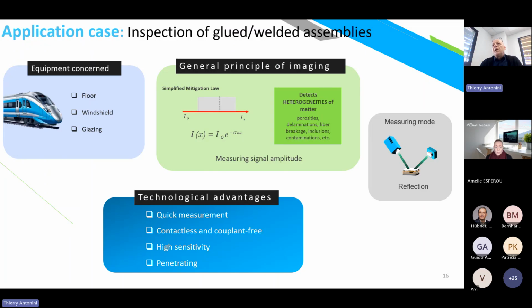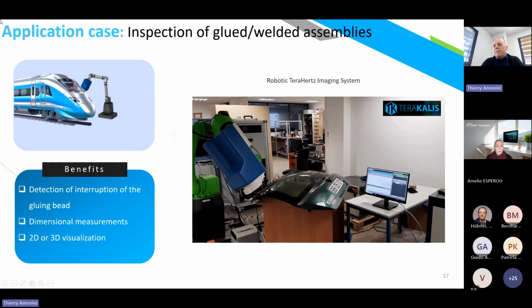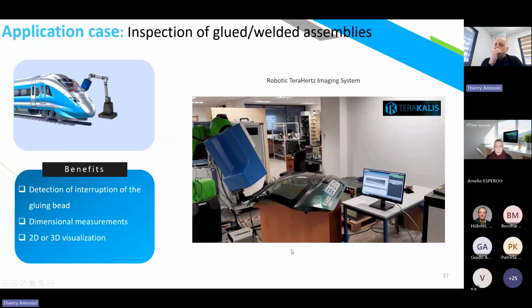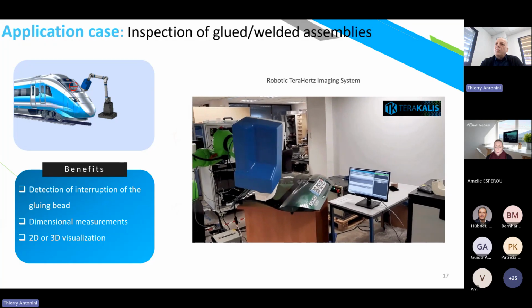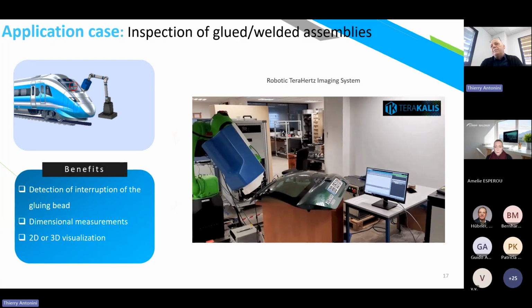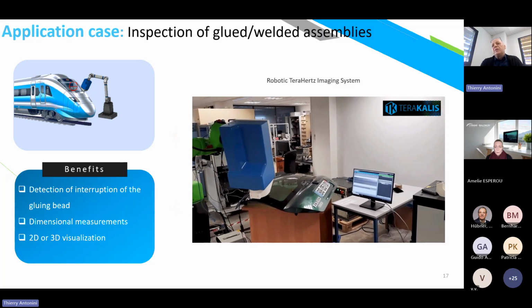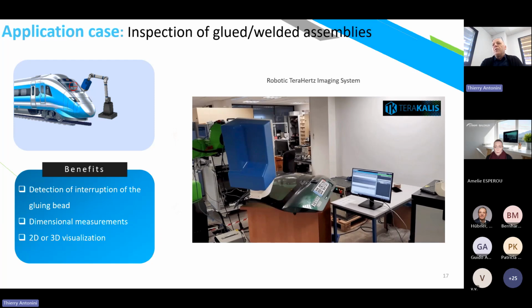Second is about assembly, and the windshield is the main target, or even the floor could be interesting to control. It's based on reflection mode. It's not thickness measurement, but imaging based on an imaging sensor. It can be done as a quick measurement, contactless and couplant free again, and penetrating all materials. Here you have another example, mainly for the automotive market. You can see the speed. The control is to detect the glue bead between glass and plastic tailgate, and we can easily detect the size of the glue bead defect inside through this technique, again non-destructive and contactless.